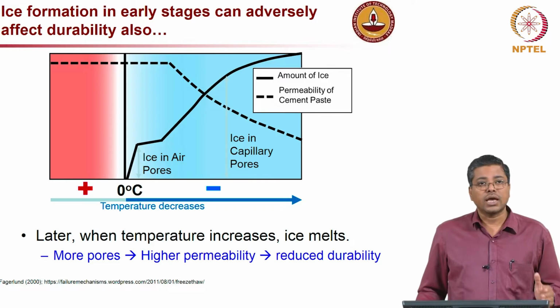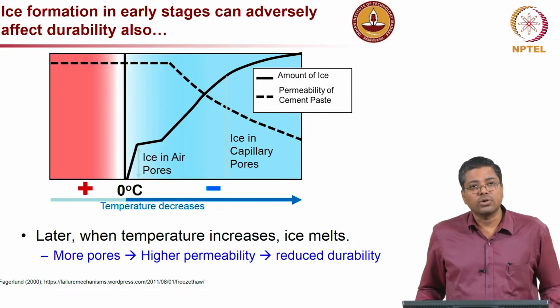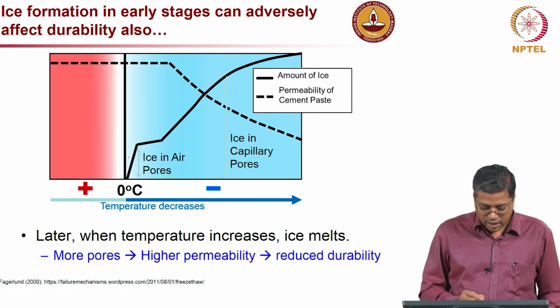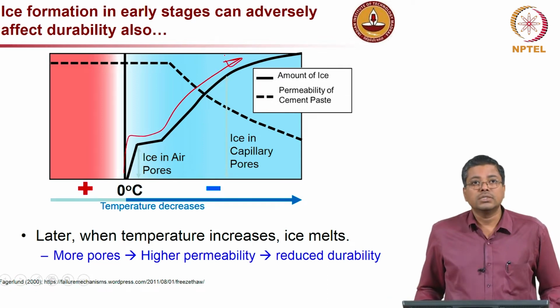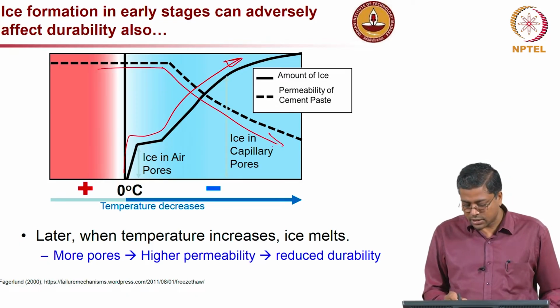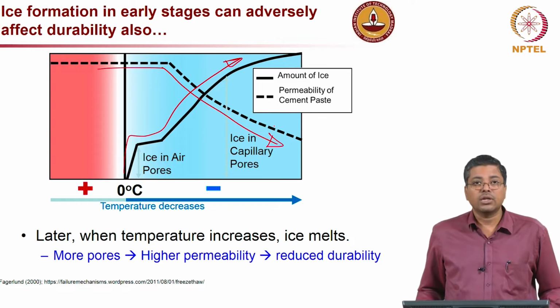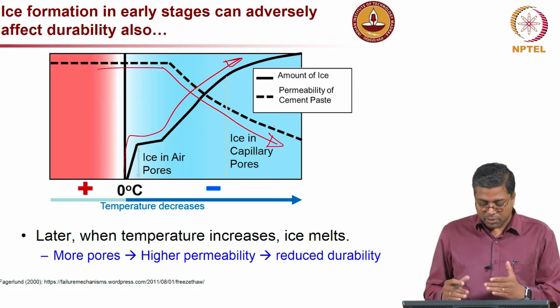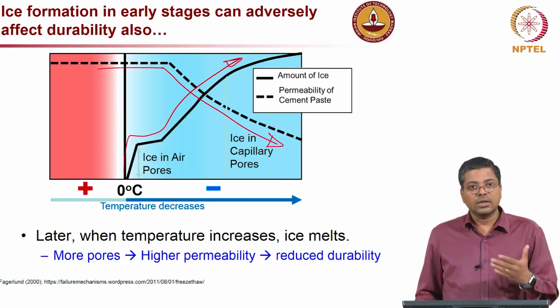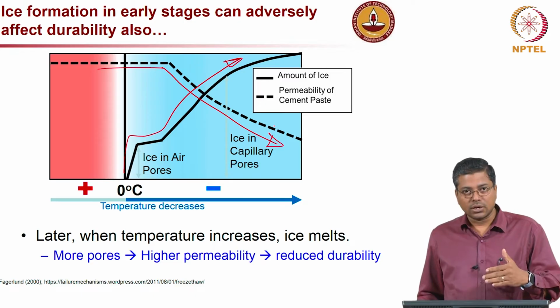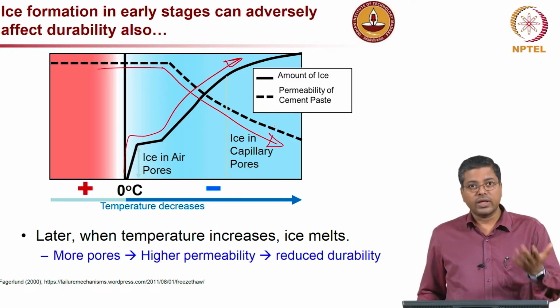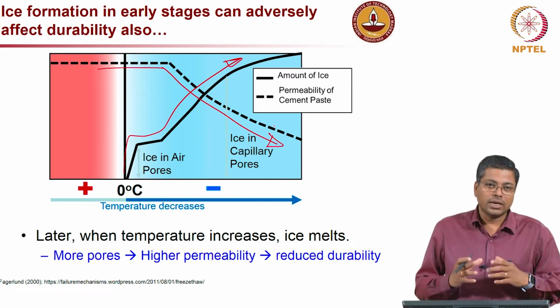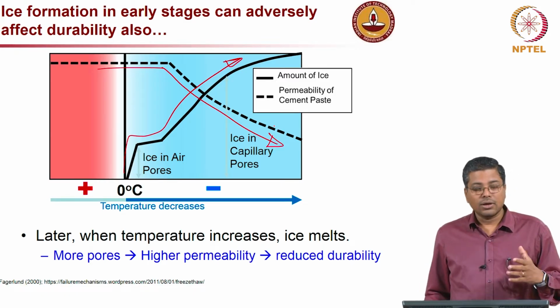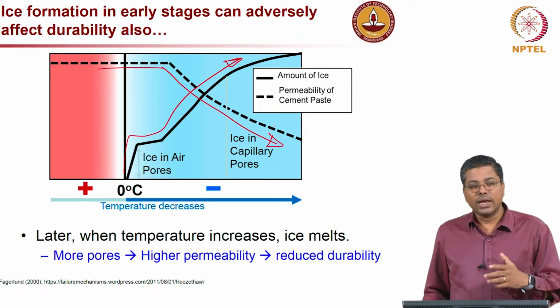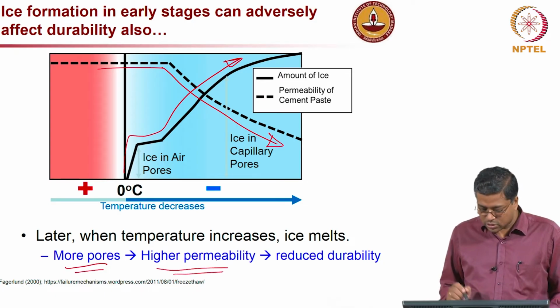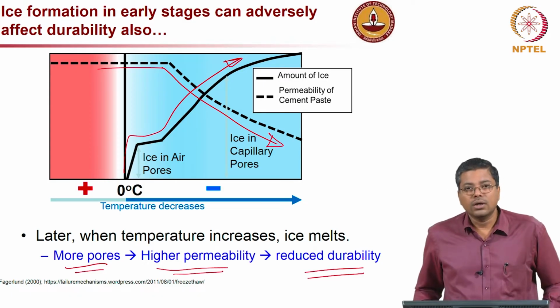Now, ice formation in early stages can, in the previous slide we were talking about strength, now it can also affect durability of concrete. How it affects durability is, if you look in the graph here, the solid curve is the amount of ice formation, and the dash curve indicates the permeability of the cement paste, or let us say concrete. So, you can see that the permeability decreases as more and more ice is formed, and in reality what will happen is, later, once this mechanism is over, after some time, if there is an increase in temperature, then the ice which is contained within the concrete will melt, become water, and that water might also evaporate at a later time. Anyway, you will end up having more pores or voids, which leads to higher permeability, and definitely you will have reduced durability in such cases.